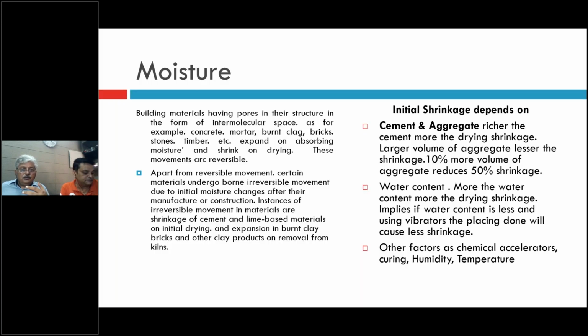But definitely there is a set procedure. You cannot go beyond that also. Otherwise your structure is going to be compromised, and definitely it will be coming under strains which it cannot withstand and may collapse prematurely. Fine. Then water content: the more the water content, the more the drying shrinkage. Implies if water content is less and a vibrator is used, the placing done will cause less shrinkage.